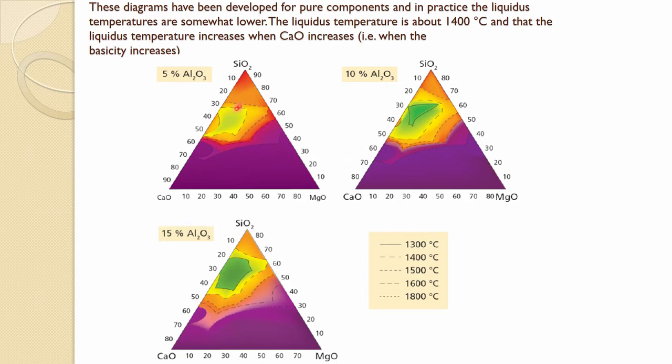So, naturally high silica increases the solidus temperature. So, melting is quite difficult. So, if you have less silica and more CaO, you can see this is your 1300 degrees Celsius region where one can have a molten slag, the liquidus temperature of that at 10% Al2O3 and some reduction in SiO2. And in this one of course at 15% you are really covering a wide range of slag compositions at 1300 degrees Celsius liquidus temperature. So, you can adjust your composition within this.